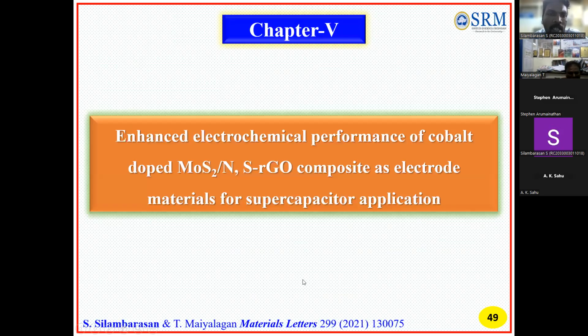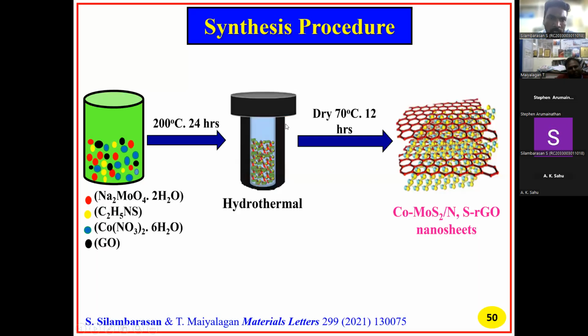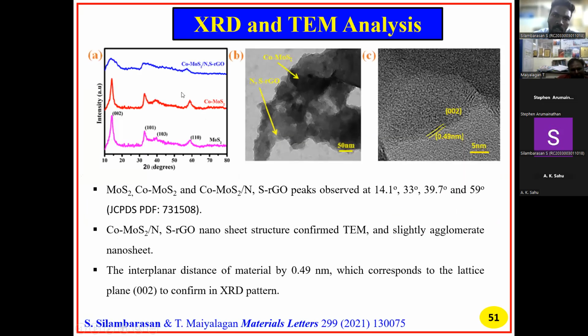Then chapter 5, the enhanced electrochemical performance of cobalt-doped MoS2 with NSRGO composite as electrode material for supercapacitor application. For the synthesis procedure, we used the hydrothermal method with the precursors sodium molybdate, thioacetamide, cobalt nitrate and GO. Then it was heated at 200 degrees for 24 hours, and finally dried in an oven, and then we got the cobalt-doped MoS2 with the NSRGO composite, and the nanosheet structure was confirmed.